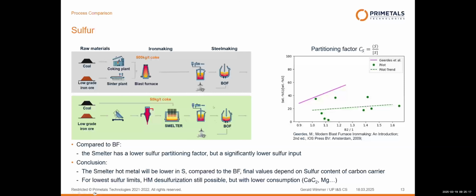Still, we have classical hot metal logistics. So if necessary, and if a very low sulfur content for the final product is required, hot metal desulfurization is also possible with the hot metal from the smelter. And as the level of sulfur is much lower, the consumption figures for the hot metal desulfurization, and also the treatment time, are definitely significantly lower than they are today when we have to desulfurize hot metal from the blast furnace.